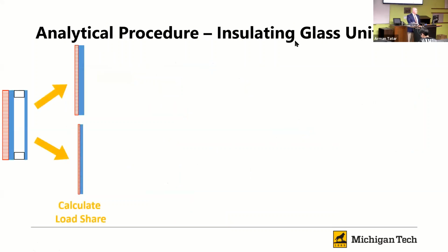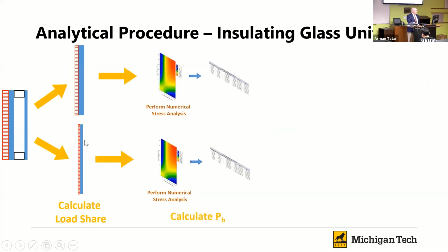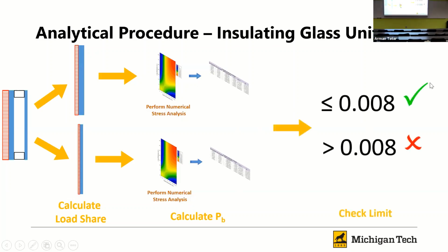We're going to see a similar procedure when we use insulating glass. With insulating glass, we now have two different pieces of glass that we have to analyze, and we also have to deal with the load sharing between those. So very simplistically, if both pieces of glass were the same thickness, then they would share the load somewhat evenly. It's not exact, but we can say it's close to 50% each. As those are different shapes or different thicknesses, that moves around. And then we perform our numerical analysis, and again, same principle, weakest link: we check the largest of the two pieces of glass and make sure we're at less than 8 in 1,000.